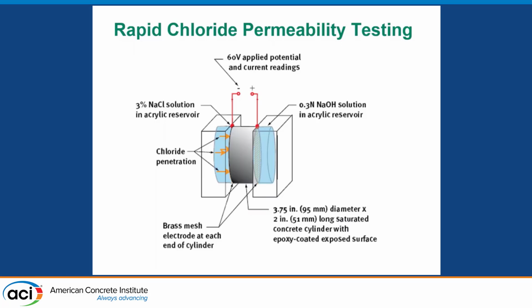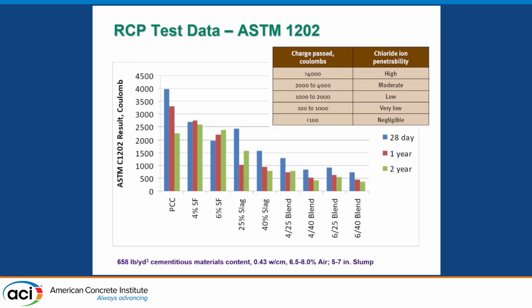And we did not take this. I don't know how many of you are familiar with this. This is why I put the test up here. You take a cylinder, you make a slice, and then you force the chlorides through it to see how fast they pass. And when we looked at the RCP data, it became really apparent to us where we were finding our sweet spots. So the Portland cement is obviously quite high, and so when we look at chloride penetrability, or how fast the chlorides are going to penetrate, certainly we're very high here.